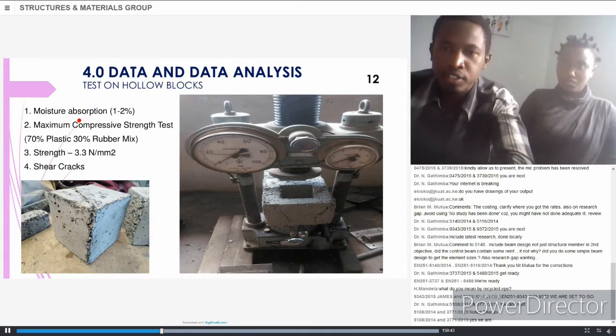With the optimum mix, that is 70% plastic and 30% rubber, we went ahead and prepared concrete hollow blocks and checked their compressive strength, which gave a value of 3.3 newtons per millimeter squared and a moisture absorption of between 1 to 2%. And when they failed in compression, they exhibited shear cracks, as you can see here and here in this diagram on the slide.